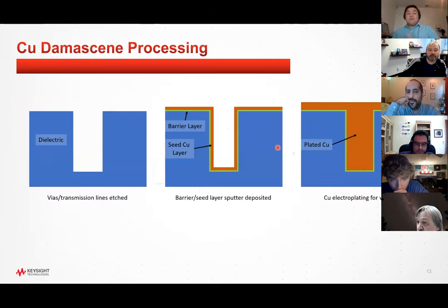And so in order to make these structures for copper interconnects, you use what's called damascene processing. The idea behind damascene processing is you have your dielectric material, often an oxide, but newer circuits tend to use stuff like different polymers, or it can vary. You have your layer of dielectric, and then you pattern it and you etch some structure into the dielectric. So in this case, imagine this is a via that you're going to use to connect two different layers. This step is where my process comes in. You use sputter deposition to put down basically a seed layer that's then later used for electroplating to fill in the structure.